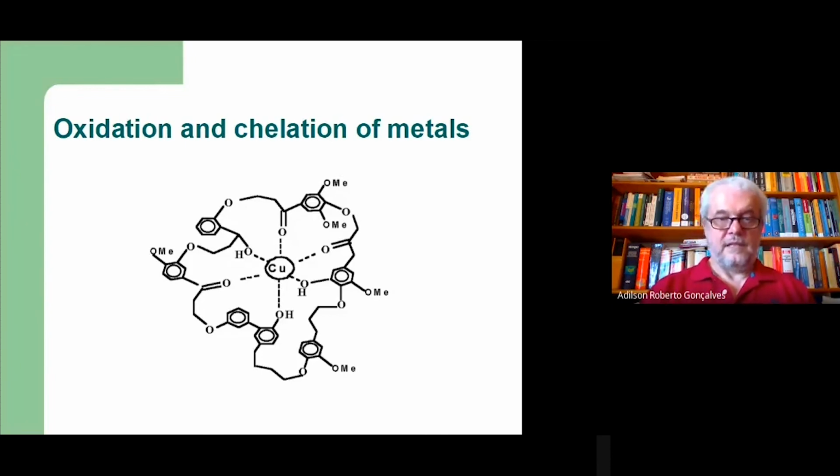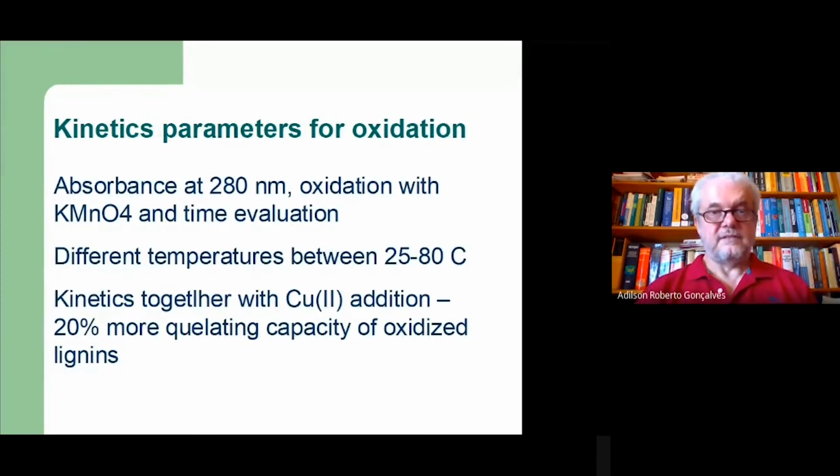We started this oxidation using kinetic parameters evaluated by the oxidation of lignin with permanganate, measured by UV absorption. We make these measurements at different times to obtain the kinetic parameters, and even the activation energy, by working at different temperatures.